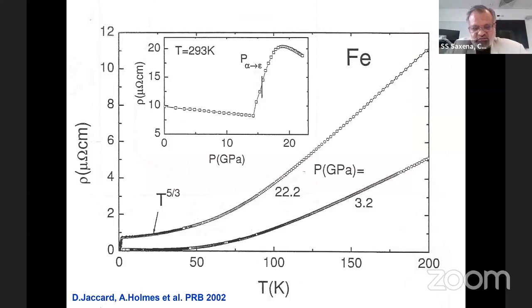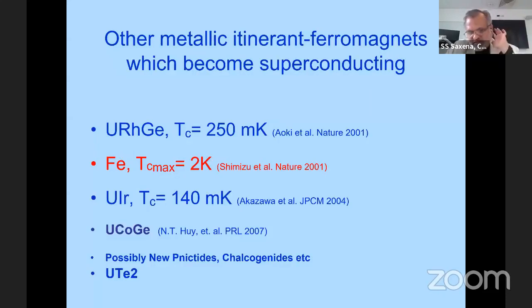But look at the resistivity of iron, and you will see that before superconductivity we again see deviation from the T-square behavior. So magnetic fluctuations are definitely there. They can be measured through neutron scattering and other methods. But even having established that method of analyzing resistivity, we can understand how these new quantum states are emerging, both in the form of superconductivity, but also in the normal state beforehand. We still have relatively few examples of ferromagnetic superconductors, and the vast majority of them are uranium materials, similar to my original work on uranium germanium 2. One debates, rightly, very specific details which are different between these materials, but generally speaking, as a universality class, they are still very similar. But the debate is still on. We need to find more answers.